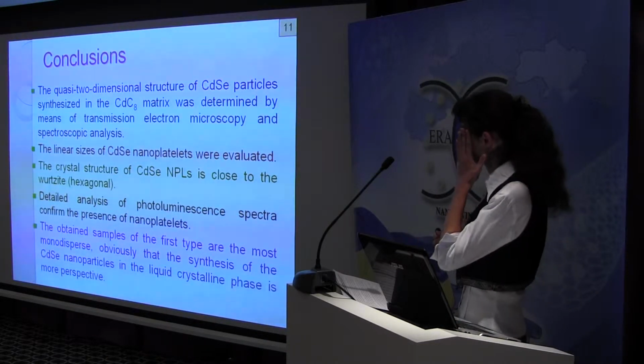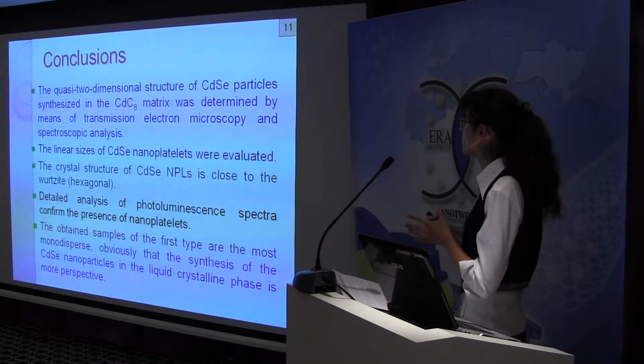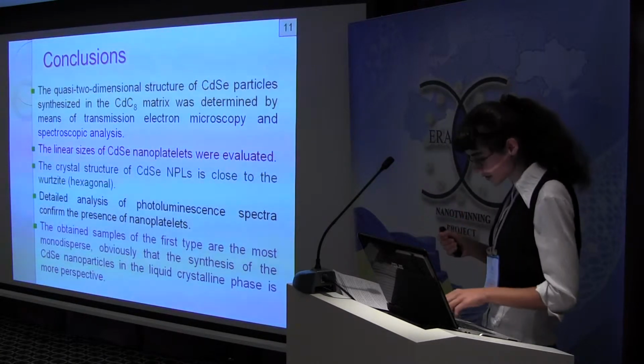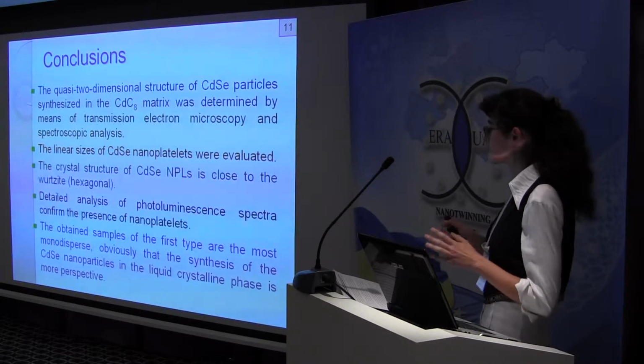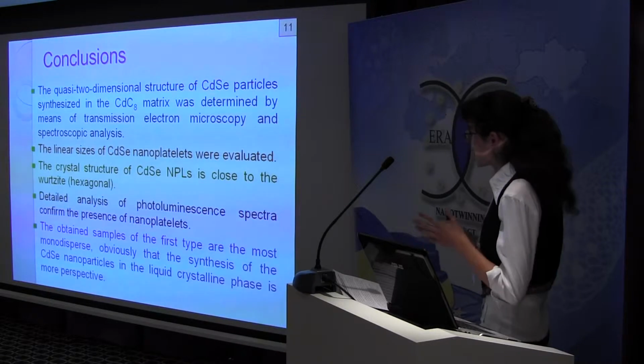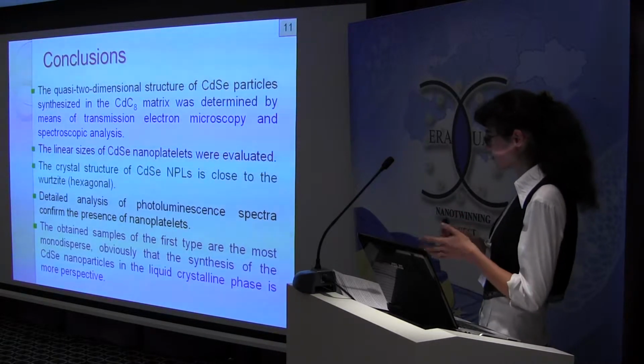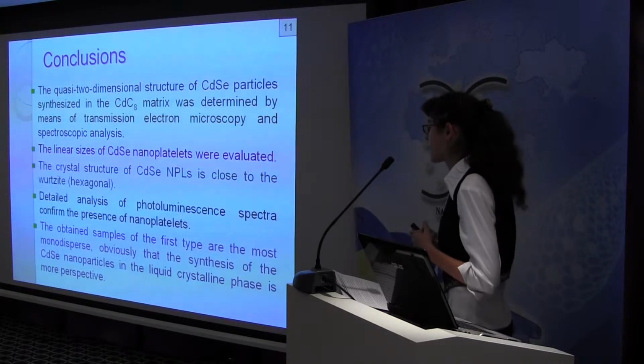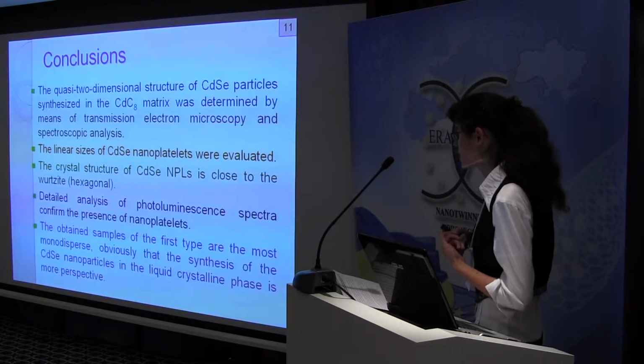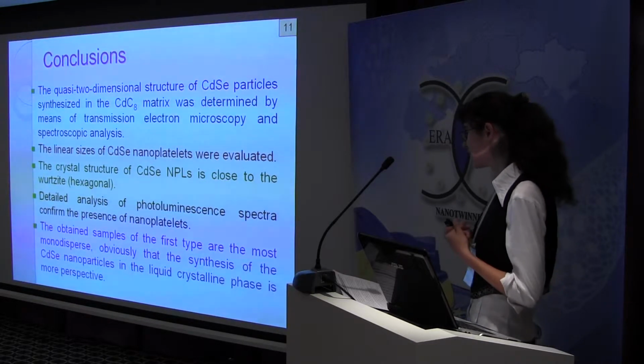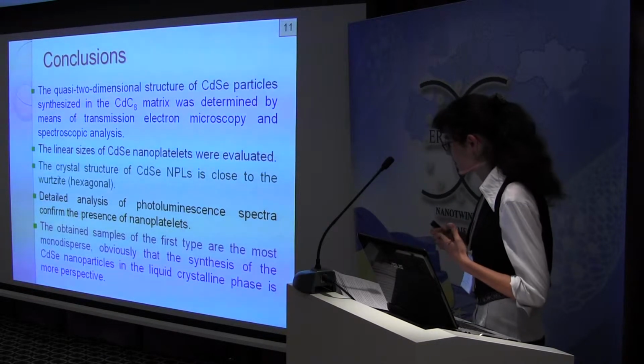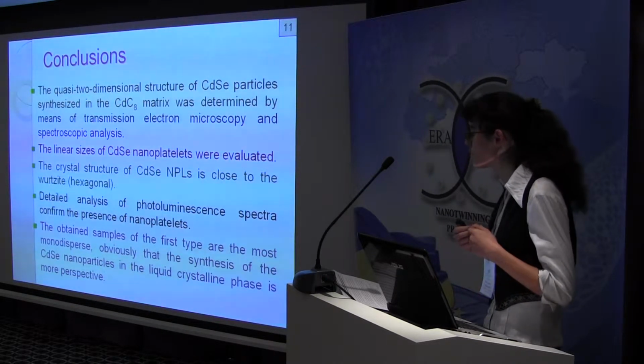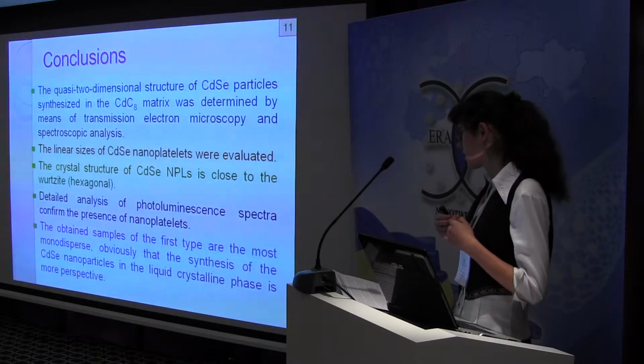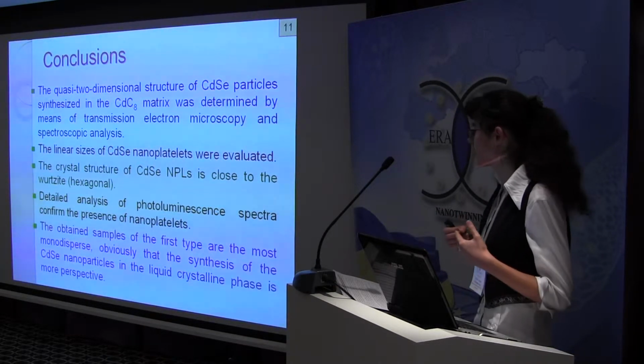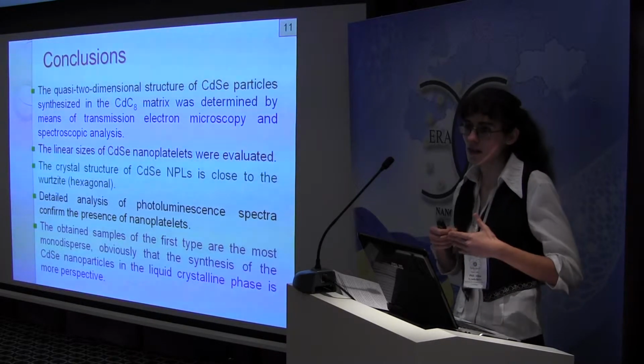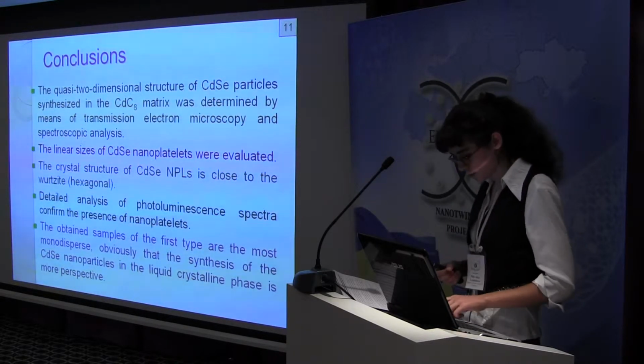Let's summarize the results. The quasi-two-dimensional structure of cadmium selenide particles was determined, and the linear sizes of cadmium selenide nanoparticles were evaluated. The crystal structure is close to Wurtzite, with nanoplatelets, and detailed analysis of photoluminescence spectra confirms the presence of nanoplatelets. The obtained samples of the first type are the most monodisperse. Obviously, the synthesis of cadmium selenide particles in the liquid crystalline phase is more prospective. Thank you for attention.